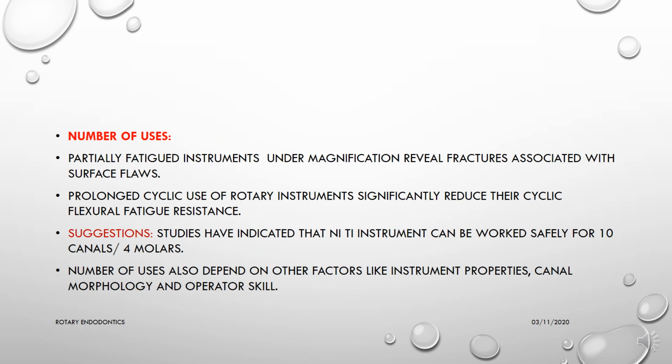How many times can rotary files be used? Partially fatigued instruments under magnification have revealed fractures associated with surface flaws. Prolonged cyclic use of rotary instruments significantly reduces their cyclic flexural fatigue resistance. Studies have indicated that NiTi instruments can be used safely for 10 canals or 4 molars, but the number of uses also depends on other factors like instrument properties, canal morphology, and operator skill. So most manufacturers suggest the rotary files be used only once to prevent instrument fracture within the canals.